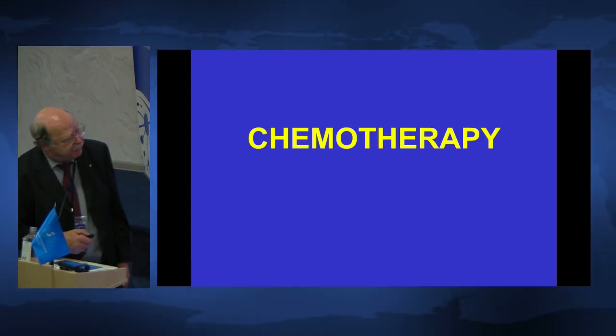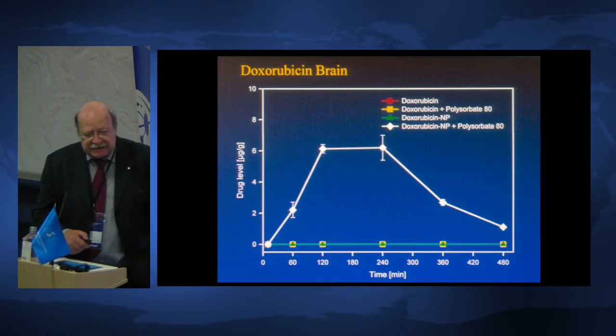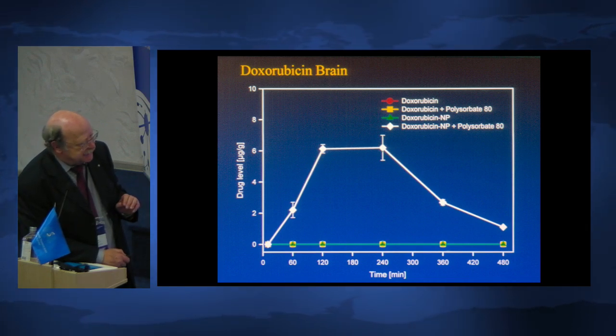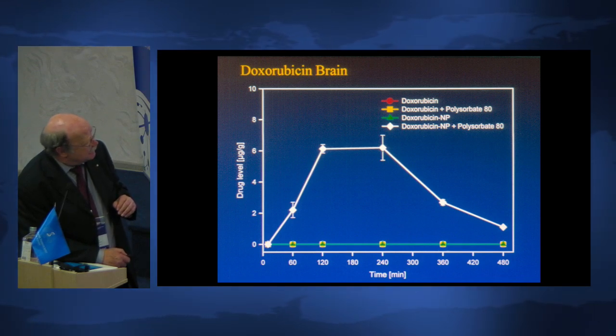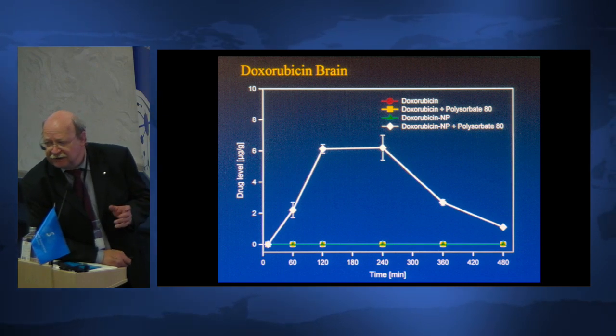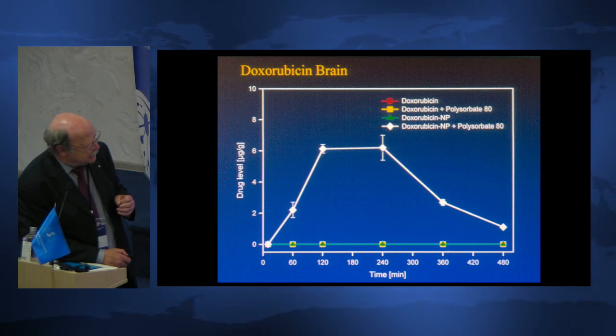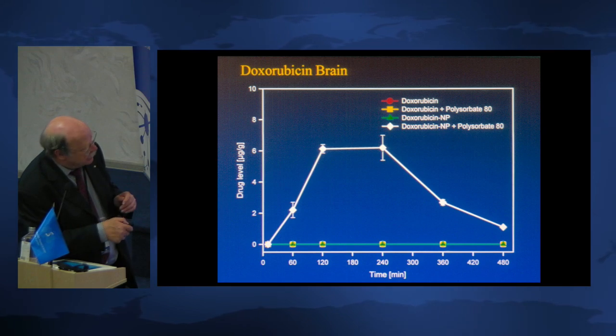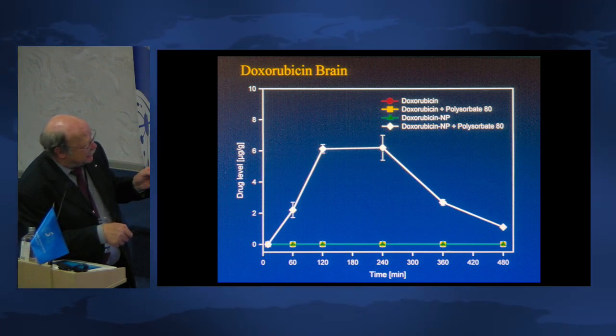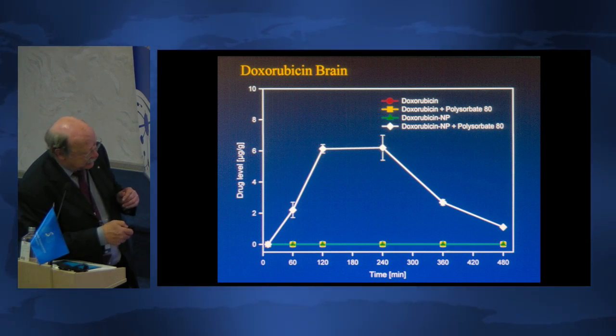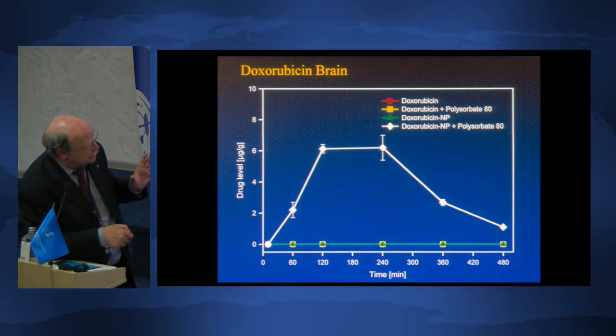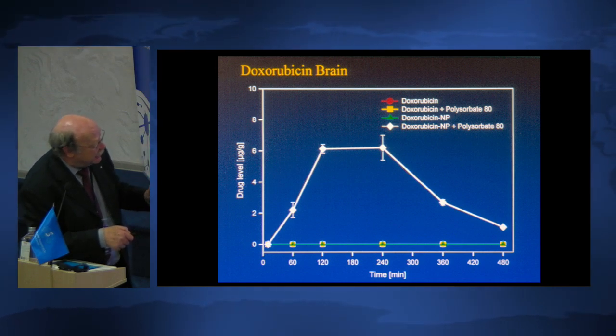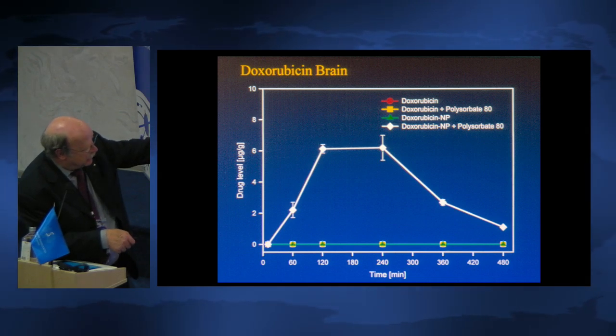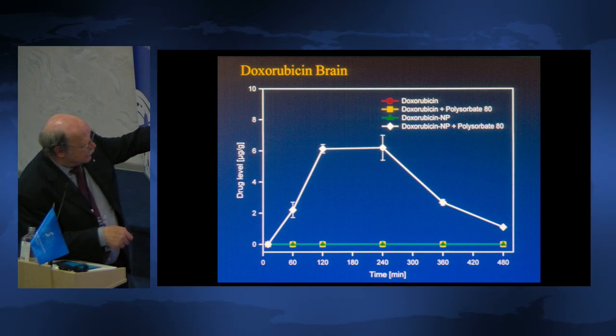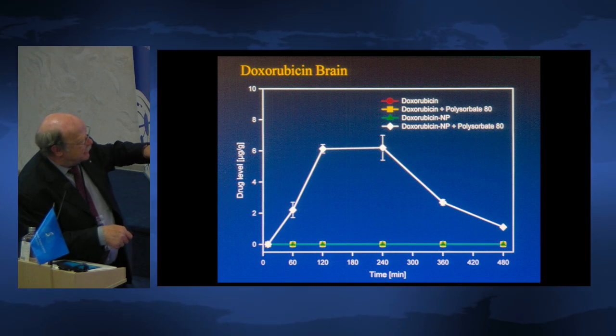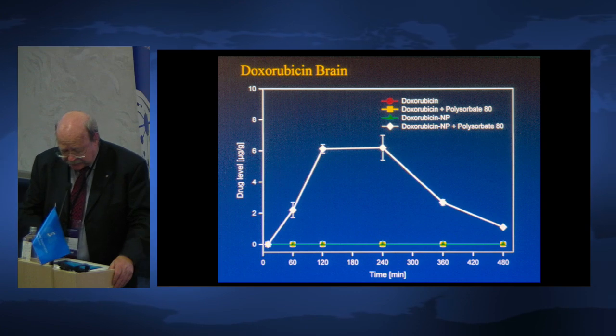Well, I'm now coming to the chemotherapy part. And what we did is binding doxorubicin, that's one of the classic drugs against all sorts of cancers. And we did this together with Svetlana Galperina, I don't know if she's in the audience. Well, anyway, she's working at the moment at Drugs Technology here in Moscow. And with her together, long time ago, we bound doxorubicin to nanoparticles and then overcoated the nanoparticles with polysorbate 80. And you can see that the controls, doxorubicin solution, doxorubicin plus polysorbate, or doxorubicin nanoparticles uncoated, had no effect. That's on the bottom of the slide. And we had a massive concentration in the brain when the particles were overcoated with polysorbate 80.